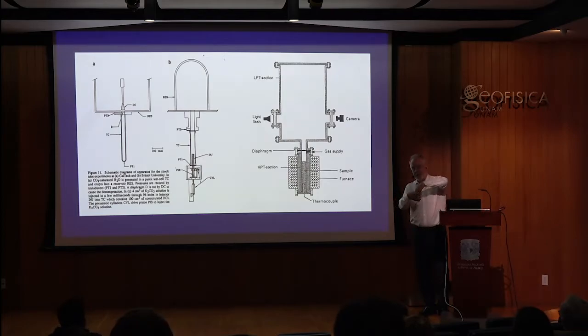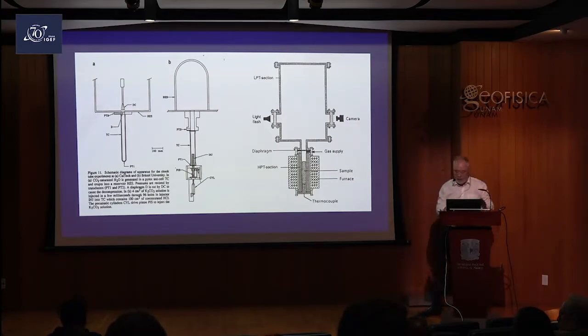She put them in two annularly arranged chambers, and she could mechanically expose them through a perforation, cause an explosive reaction of potassium chloride solution and sulfuric acid, and cause a foamed flow. They were doing anything possible, mechanically or chemically, to cause a foamed flow because they believed the foam flow was somehow the key to understanding the dynamics of eruption.